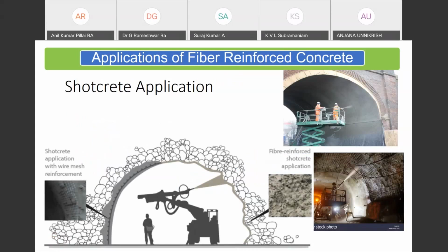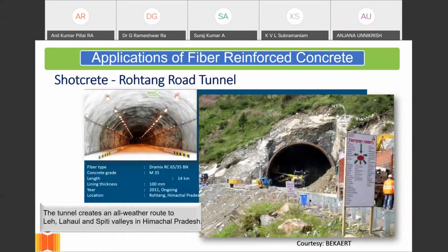Now, whenever we have tunnels, as the excavation or blasting takes place, the rock mass has to be stabilized. And the way it's traditionally done is using conventional reinforcement and then gunniting. So one creates a layer of concrete, which is gunnited using conventional reinforcement. Now, the newer application is to shotcrete it, where basically concrete is directly shot onto the blasted or excavated surface, and it contains fibers in it. So there's no need to put in a reinforcing mesh. And using this shotcreting technology with fibers, several tunnels have already been made in India, including that all-weather route in Leh, and Lahul, Spiti Valley tunnels in Himachal Pradesh, Jammu, have been made with this shotcreting technology, where steel fibers have been used instead of conventional steel reinforcement.